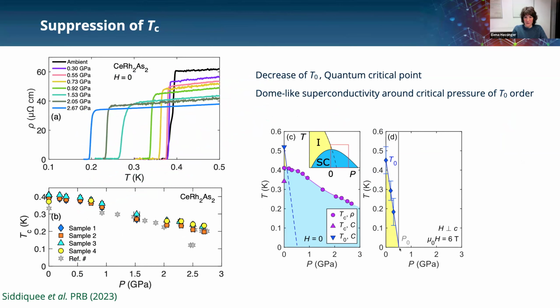at roughly 0.5 GPa. Now, we measured the superconducting transition in zero field, and these are all the pressures. So pressure increases like this, and we go up to 2.7 GPa, and TC is roughly suppressed by a factor of 2. And then we can trace the phase diagram at zero field, shown here on the left, where you see that the superconductivity basically evolves as a dome around this critical pressure. And just as a side remark, we've measured 4 samples in our study as a function of pressure, and we did not confirm this decrease of TC that was reported in the CeRh2As2 paper.